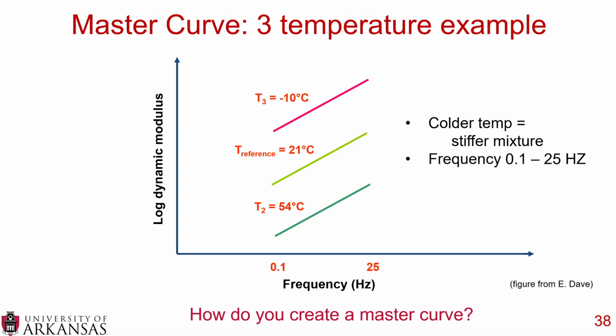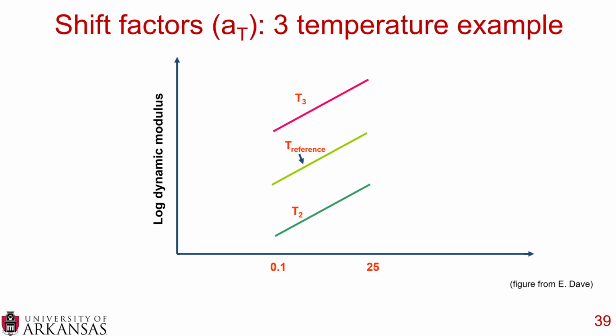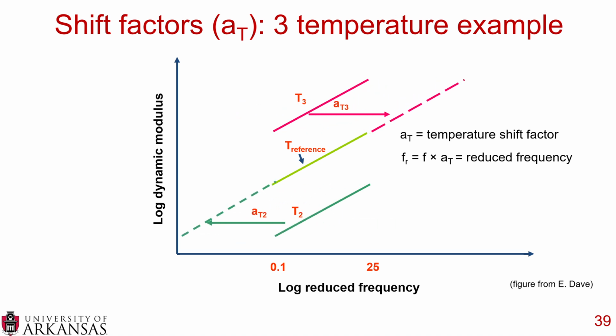Now what can you do to create a master curve? Well, you take these three sets of data and you simply shift it. So you use a shift factor, which is A sub t, and using that three temperature example, your reference temperature is the middle temperature, A sub t is the temperature shift factor, and then F sub r is the original frequency times A sub t, and you get the reduced frequency. And you can see here, the curves shift.